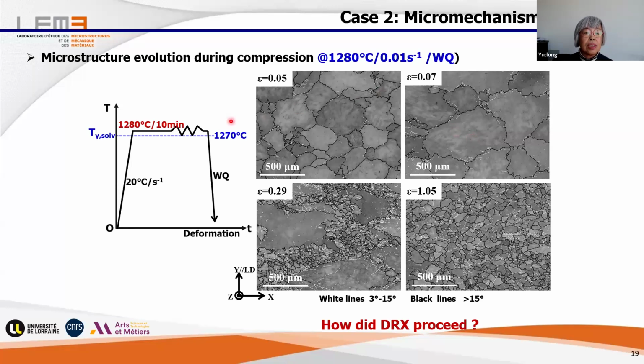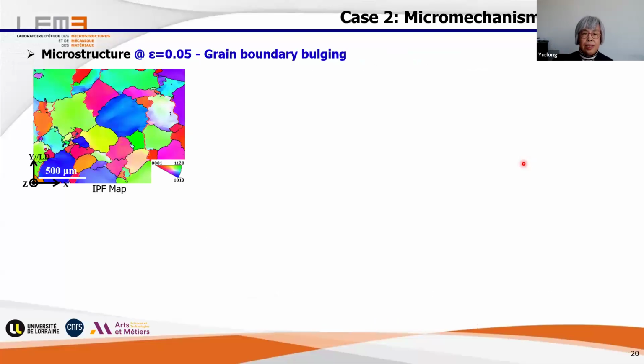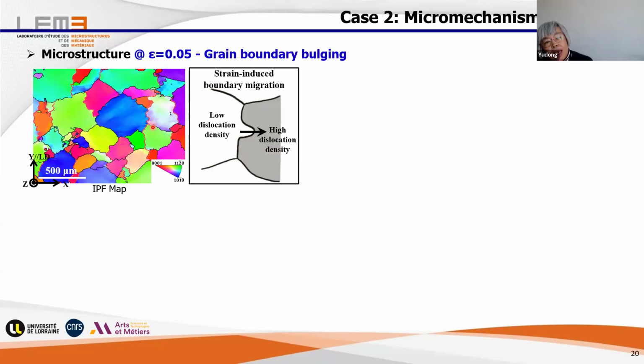When we do the compression, with the progress of the deformation, we see the microstructure changes. With all these changes, we would like to know what happened behind to drive such a microstructure change, so now we made a step analysis. One, at the very beginning of the deformation, the change is only at the grain boundaries. We can see the boundaries become not smooth at all, but more serrated. We say it's bulged. In most textbooks, such a bulge is called strain-induced boundary migration.